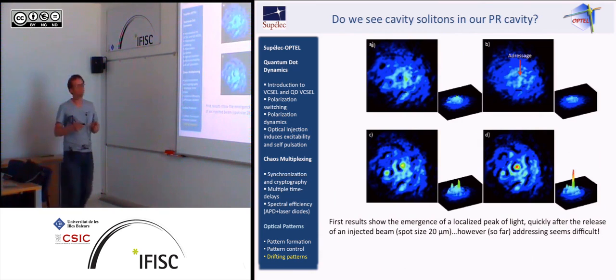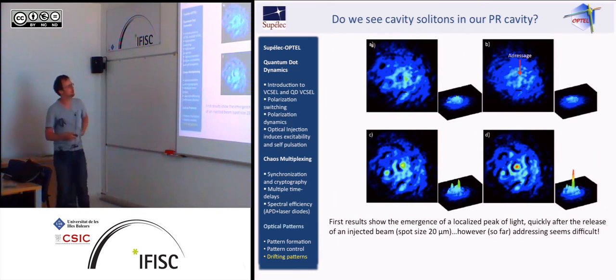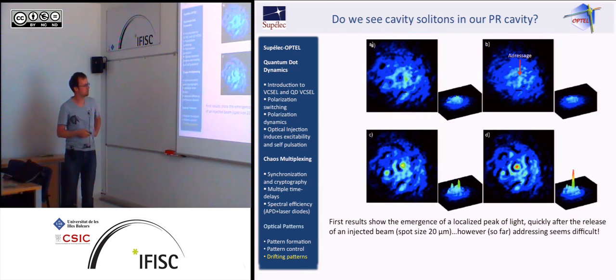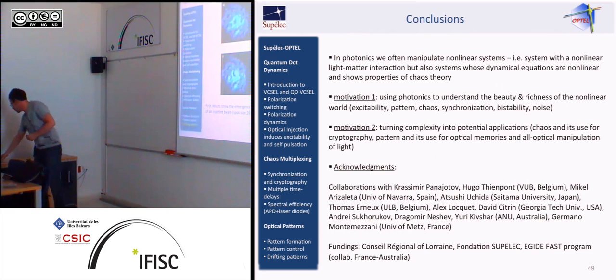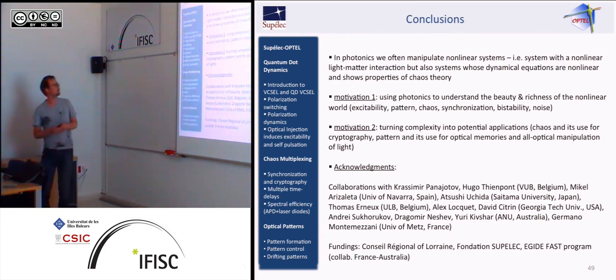So, just to tell you a last thing that we have been doing is to try these localized structures. And this is a very preliminary result. So, you have the homogeneous state, and you know in localized structure, the system should normally move to the pattern, but you want to send light along a single peak. And what happens is that indeed we see that the light stays. To tell you the truth, the light stays for minutes. Yes, in the peak, and not for hours, so most probably there's something wrong there. So that's all. I'm sorry I was a little bit long, but I thank you for your careful attention.